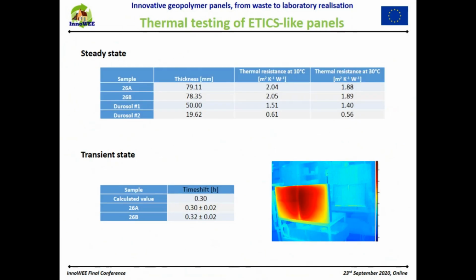The results that we obtained are good both for the steady state, as the values are compatible with the measurements on the laboratory samples that I showed before, and are good also for the transient state, as the calculated value is very, very close to the measured one.